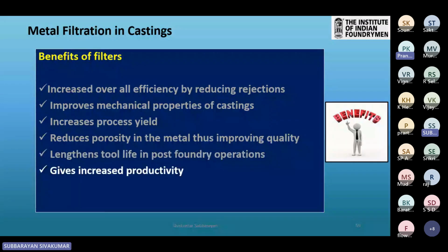It gives increased productivity. If you take ductile iron, when I introduce the filter, it filters out drastically the dross, which is a killer in the post fettling operation. Till the dross is fully removed, our NDT team will not clear the casting. Normal fettling will take 8 hours, and dross cleaning, dross grinding, will take another 8 hours. So when we introduce a proper type of filter, the right category of filter, it filters out the dross and improves the productivity directly.